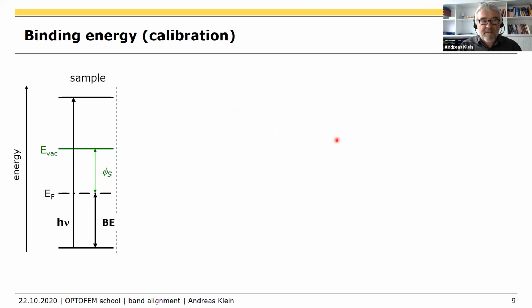Okay. And now we look at the binding energy calibration of our XPS. So the situation here, this is maybe our vacuum level. This is our core level of the electron. This is somewhere the Fermi level in our material. And we want to know this. This is the binding energy. And we want to know this with respect to the Fermi energy.